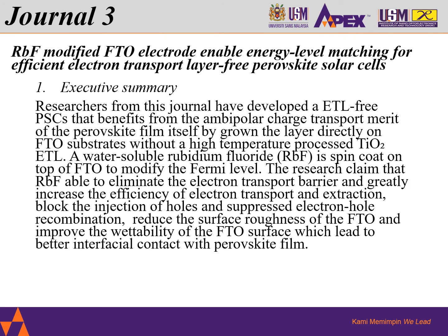The researchers from this journal believe that by removing the ETL from the PSC structure and growing the perovskite layer on the FTO substrate directly, without going through a high temperature process for the TiO2 ETL, the device will benefit from the ambipolar charge transport merit of the perovskite film itself.